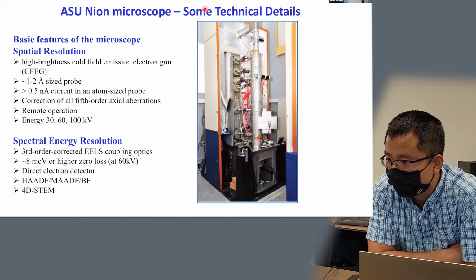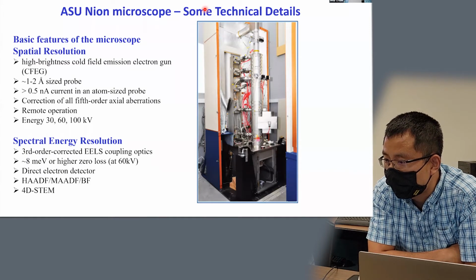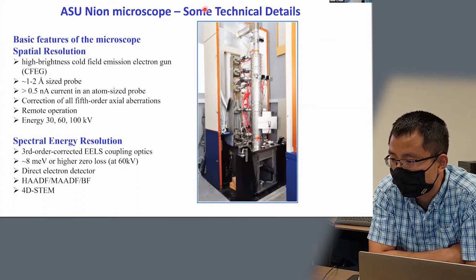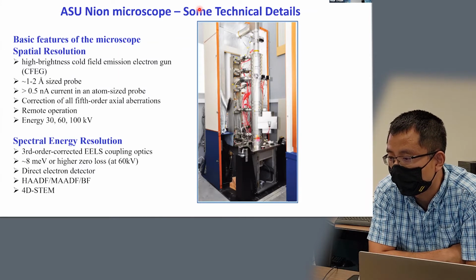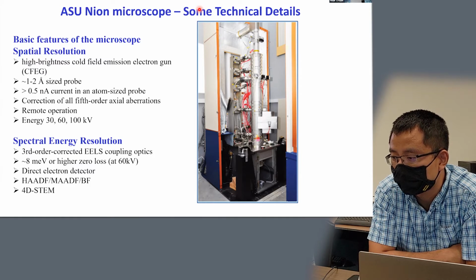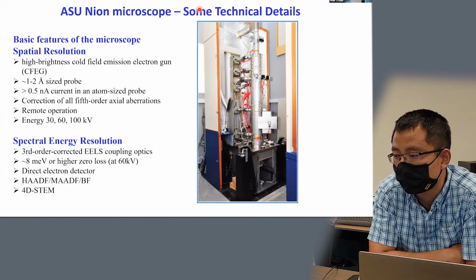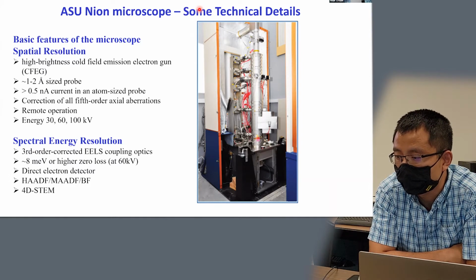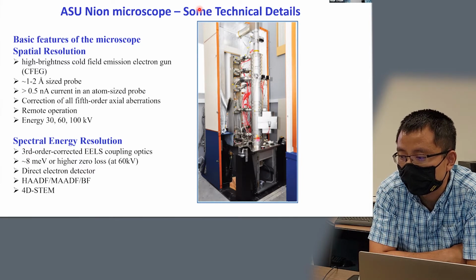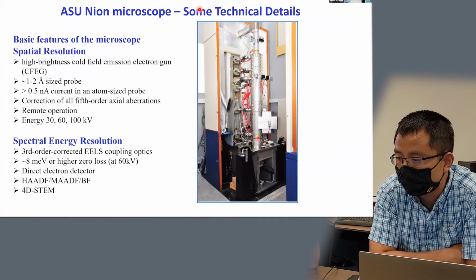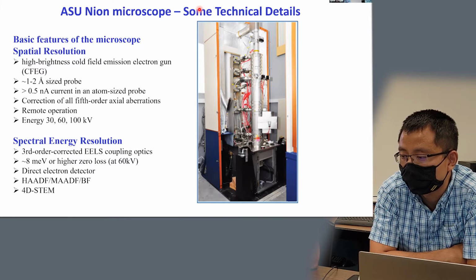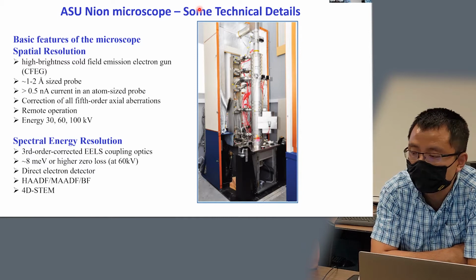So the ASU Nion Microscope is equipped with a high brightness cold field emission gun, which offers a very decent atomic size probe with a size of about 1 to 2 angstrom at a high current larger than 0.5 nanoampere. The aberrations can be corrected up to the 5th order, and it operates at 3 different voltages of 30, 60, and 100 kV, which is good for beam-sensitive materials. In terms of energy resolution, we can achieve as high as 8 millielectron volt at the zero loss peak at 60 kV. With the new direct electron detector, we can do a lot of fancy techniques, such as 4D STEM, along with the normal high-angle, medium-angle annular dark field, and bright field imaging modes.